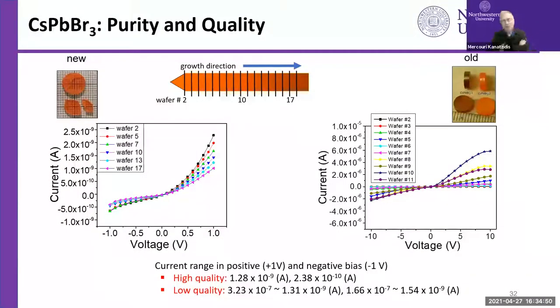So one concern is how good is the material across the crystal? So this is a study where we cut crystals, slices like a salami along the ingot, and then we measure the IV current. And you see here, there is some variation from the bottom and then to the top. But more or less, I think it is a reasonable variation from top to bottom.